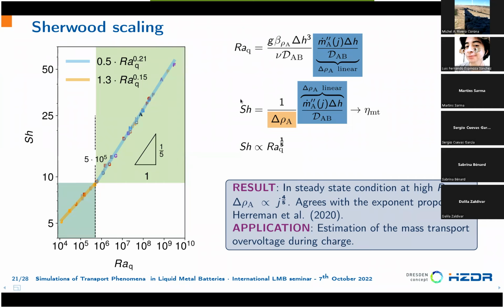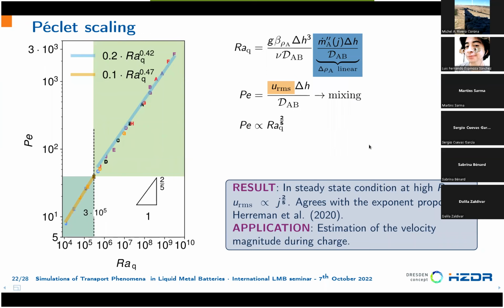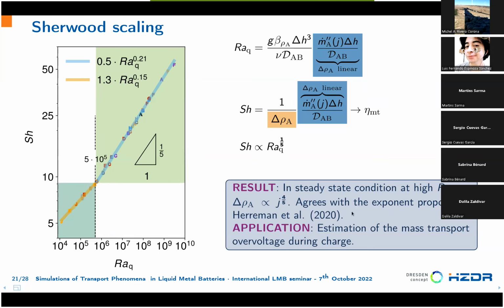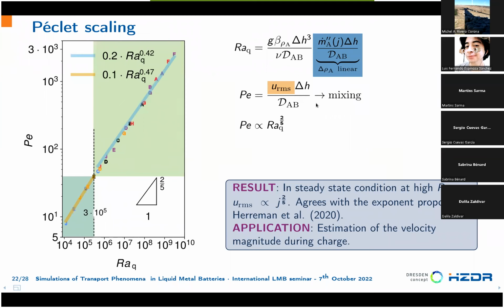This is very relevant, as already discussed, for the computation of the mass transport overpotential. If someone knows the material properties of the electrode and the current density at which it's running, then with this correlation they can simply compute the Sherwood number, then from the Sherwood number compute the concentration difference, and from the concentration difference compute the mass transport overvoltage. For the Peclet scaling that is related to the mixing, we also find a 2/5 scaling of the flux Rayleigh number, which corresponds in this case to a current exponent of 2/5, and that agrees as well with Hermann et al. This again allows us, knowing the correlation, to compute the velocity inside the layer and know if, for example, solutal convection is able to affect the interface, or which magnitude of flow drives inside the layer. And now we move to the 3D electrode.